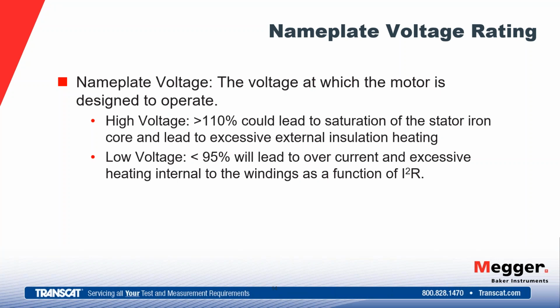Too high a voltage can lead to saturation of the iron core and leads to excessive heating from the inside out. So as we apply more voltage than what the field is designed for, we get that rotating magnetic field. The strength of that magnetic field is directly related to the voltage that we're applying to it. And if we're applying more voltage than is needed, at some point we will saturate the iron core, causing eddy currents and hysteresis losses in the iron core, which cause heating.